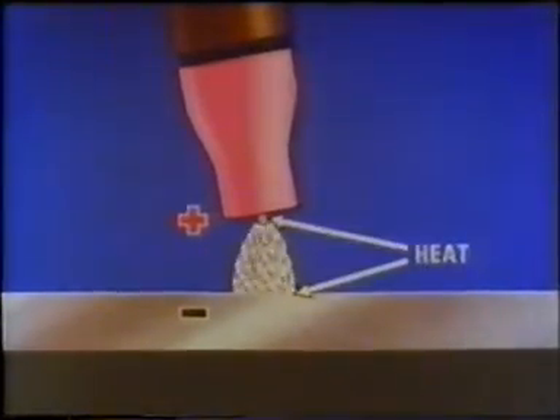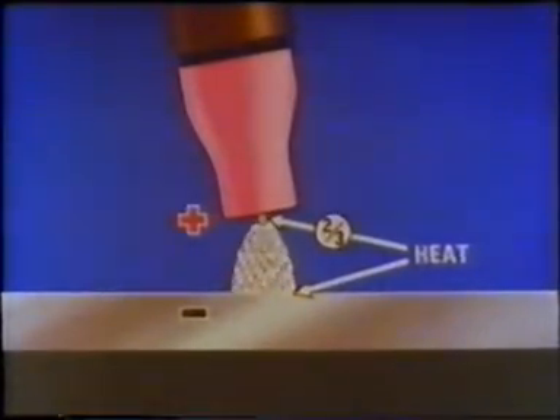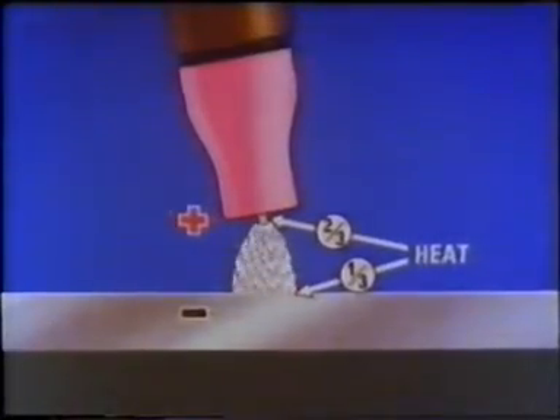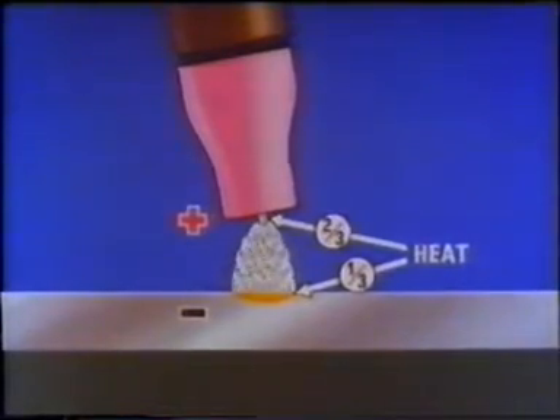First, the electrode can become so hot from the electron bombardment that it begins to melt despite its high melting point. Here it is in slow motion. The electrode is positive, it's being bombarded by electrons, and so it's overheating. It waves about, making welding control difficult. Finally, it melts completely and contaminates the weld. In fact, with this polarity, of the heat generated, 2/3 is in the electrode and only 1/3 in the workpiece. This produces the second disadvantage, shallow penetration into the parent metal.